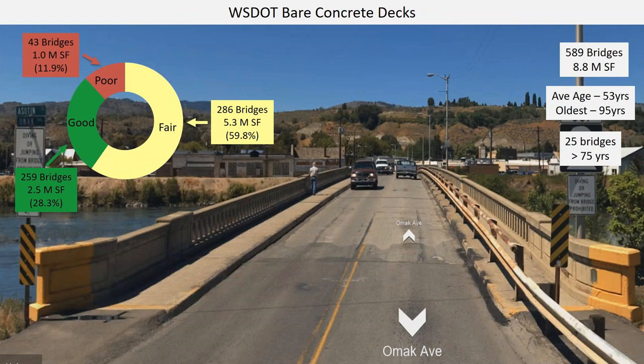So when you look at the bare concrete decks, if you just look at an inventory of those, we have about 43 bridges that are currently in poor condition. Vast majority are in fair condition with a small percentage in good condition. Again, remember, these were built prior to 1980, so they have an average age now of 53. This particular bridge in Omak is nearly 95 years old and is still in decent shape.